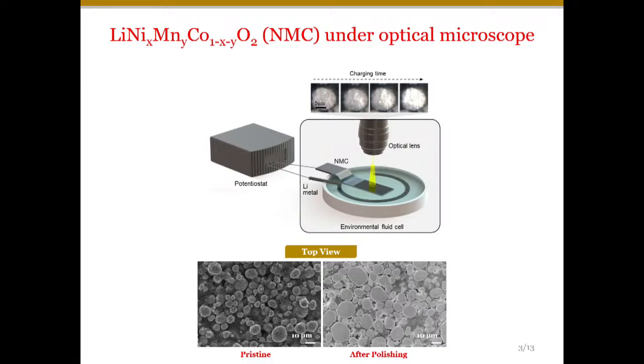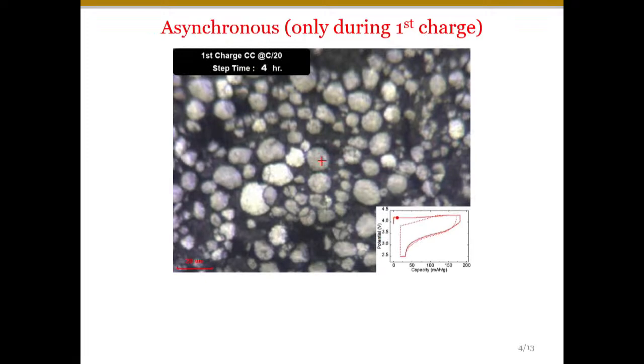In this work, we polished the top surface of the cathode and observed it under an optical microscope as we charge and discharge. What we observed was there is a change in optical intensity of particles as they charge. This change in intensity is more of what we call asynchronous, because intensity changes randomly within particles.